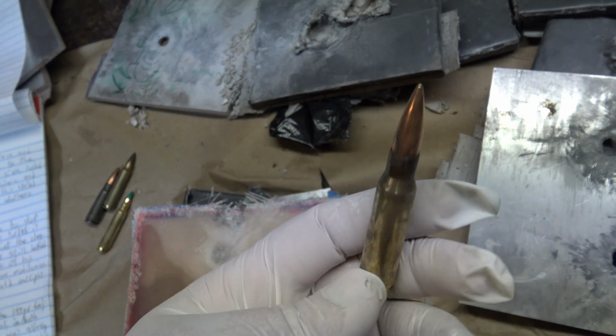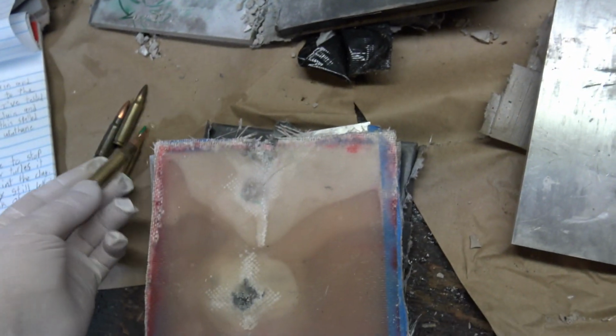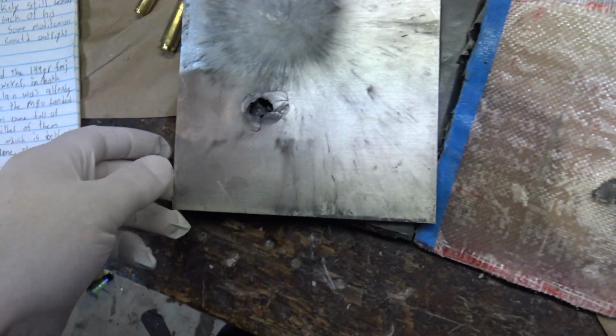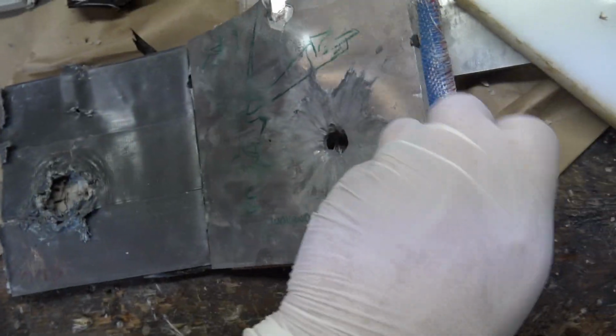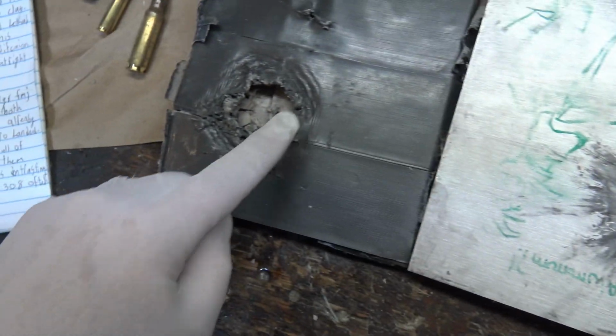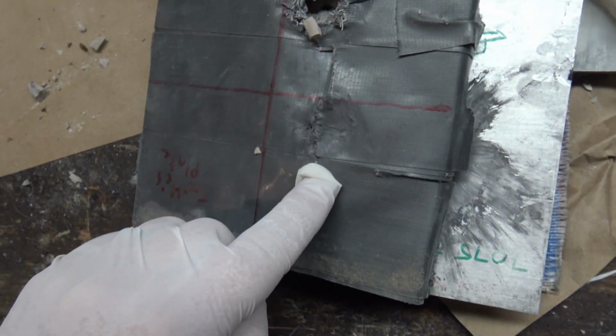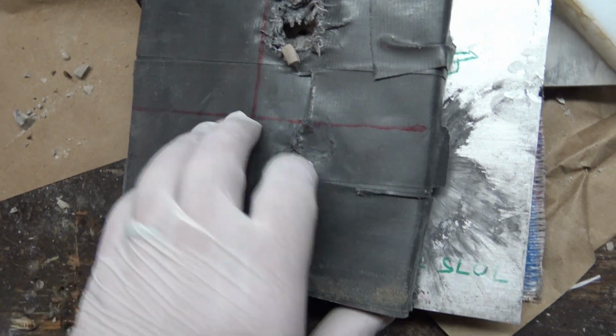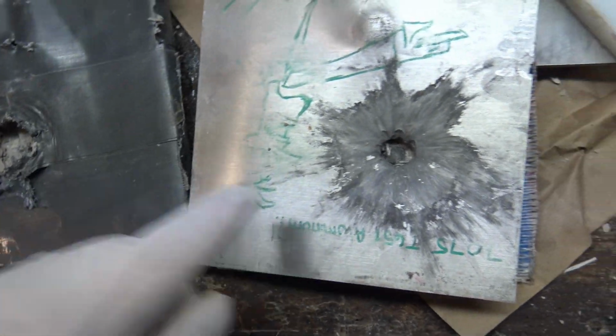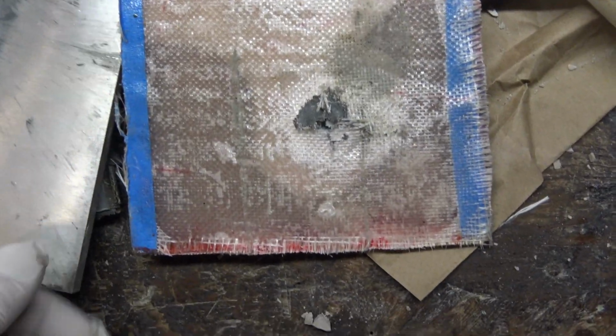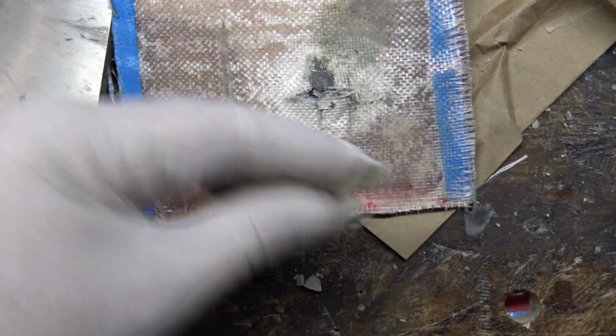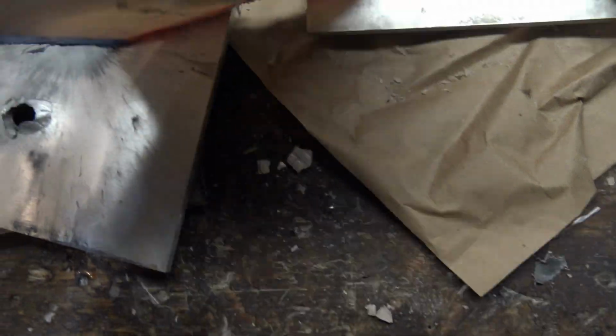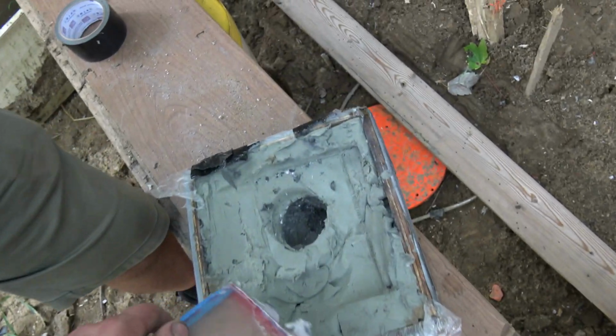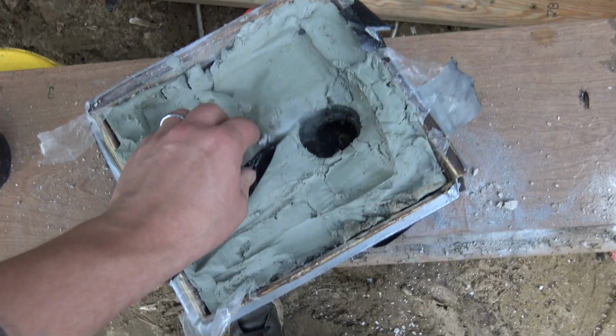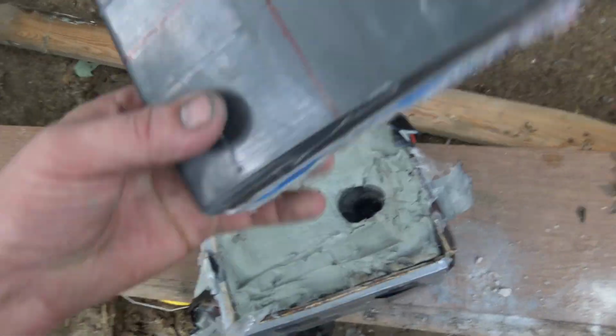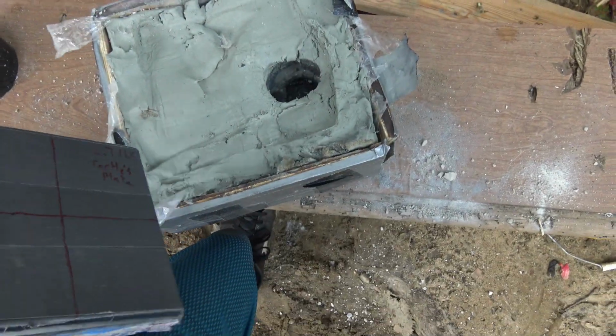I also want to note that none of these plates stopped the 147 grain full metal jacket 308, also known as the M80. However, in both the tests where I shot it, the porcelain was already damaged close to the area where the M80 landed, and the impact on the clay was a cone full of lead spray and metal shrapnel. Neither of them blew through the clay witness or out the back, which I do find interesting because if you've seen plenty of other videos I've done, mainly the Myanmar with Love, when I test the 308, it often will just absolutely destroy my clay witness or blow it out through the side.